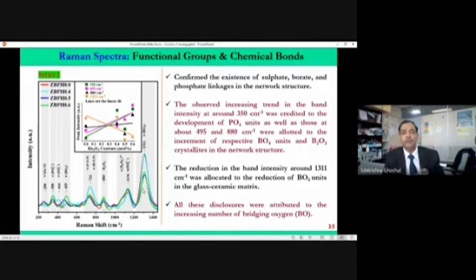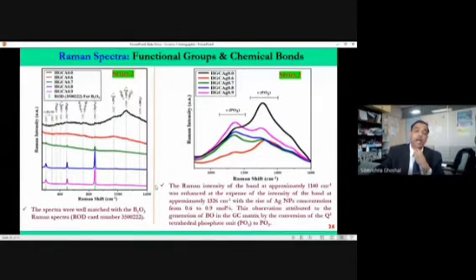Then we go to the Raman measurement. In the Raman, we also see the same peak, and we confirm that these crystallites have formed. Then we analyze the Raman peaks more and more to see where is the phosphate, where is the borate, because borate and phosphate are very interesting materials. They can form different kinds of units, PO2, PO3, PO4. Similarly, borate, BO2, BO3, BO4. But remember, BO4 and PO4, that means phosphate in four and boron in four, are the most stable units.